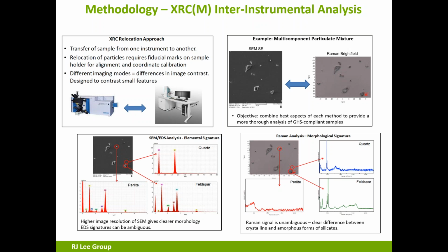We're looking for pure, unadulterated, uncontaminated crystalline silica quartz. So if we're looking for that, we know that's got to be Si rich, silica rich, and oxygen greater than 90%. So we find the particles and we look at the elemental signatures. One is quartz, one is feldspar, one is perlite. This is just an example using a perlite product. We do the same thing with the Raman, and the Raman is unambiguous. It can actually look at the crystalline structure and determine whether or not that particle is specifically quartz, perlite, or feldspar. So the combination of these two analysis methods gives us a very definitive means of quantifying the amount of particulate that is in a certain weight percent and size.